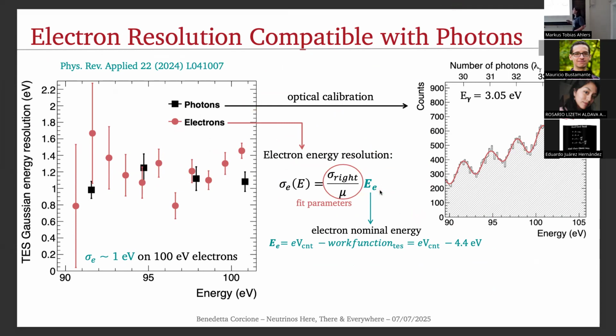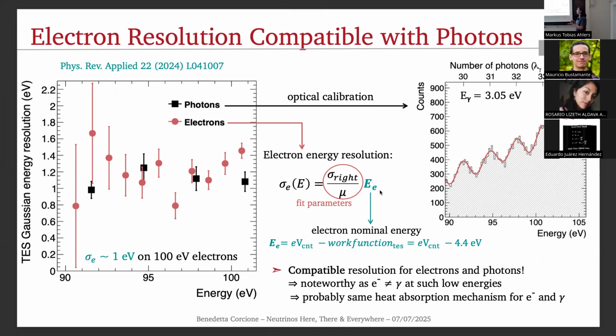And we were pleasantly surprised to see that our TES has a compatibility in terms of energy resolution for photons and electrons in the same energy range. The photon data were acquired by an optical calibration of the device. I want to stress that having found such compatibility is noteworthy because at such low energies, electrons and photons interact in a completely different way with matter. So this may hint that the heat absorption mechanism of the device is the same for both electrons and photons.